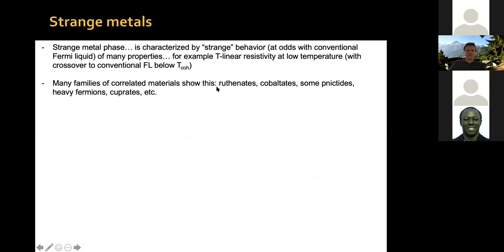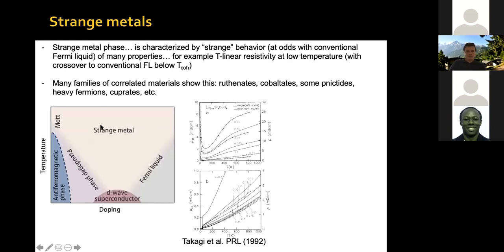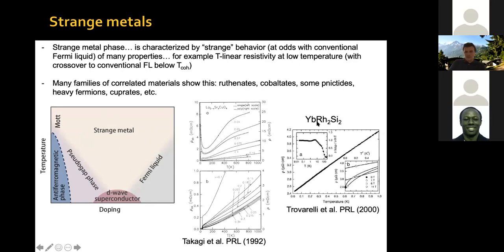Okay? This occurs in many families of correlated materials: ruthenates, cobaltates, pnictides, heavy fermions, cuprates, etc. It is this big region in the phase diagram of the cuprate superconductors, for example. Here's some of the original data where you see the resistivity for some dopings in this region above the superconducting dome is very linear, okay? In this heavy fermion, for example, you measure the resistivity versus temperature, and you see that it's linear down to the lowest temperature they can measure, okay? This is a very unusual behavior for a Fermi liquid to exhibit.